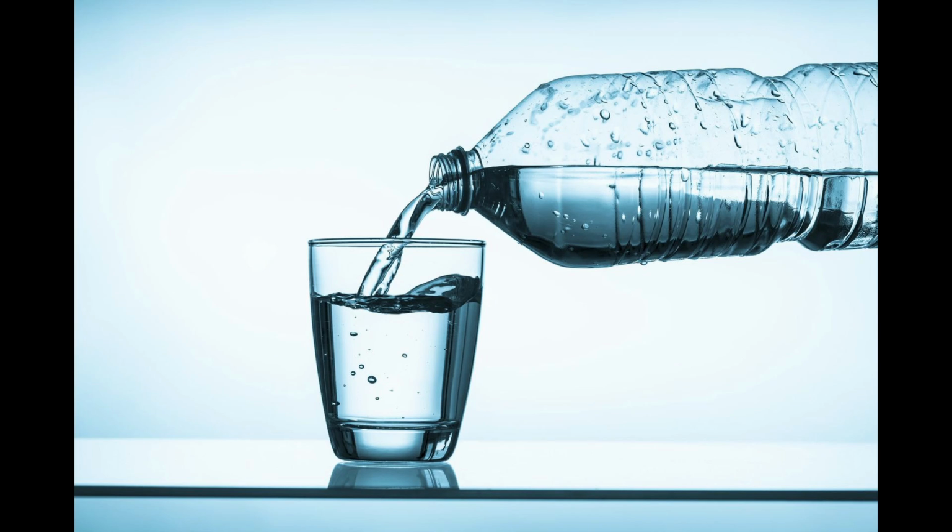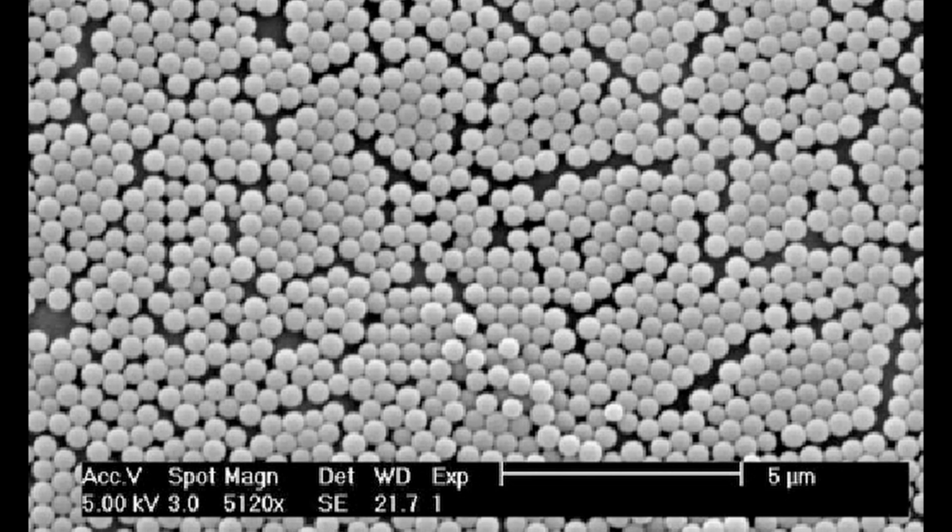Now, as you might have guessed from the long chain hydrocarbon nature of these molecules, or from the smell of anyone having acrylic nails done, none of these compounds is water soluble in any significant way. In fact, if you remember from the history section, the first acrylic paints were solvent based, so how can we have this reputation of acrylics being water based? If we actually examine acrylic polymers under an electron microscope, we find that several hundred of these long chains come together to form submicron sized spheres.